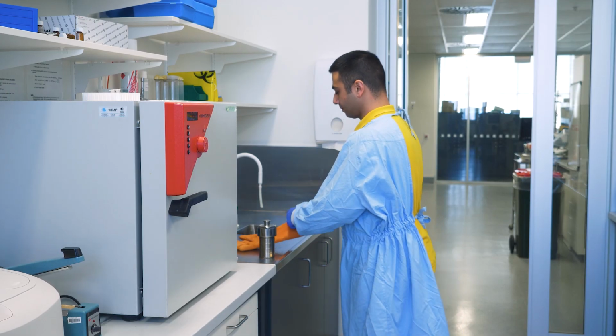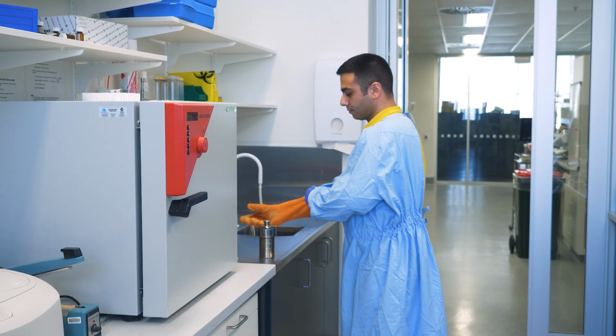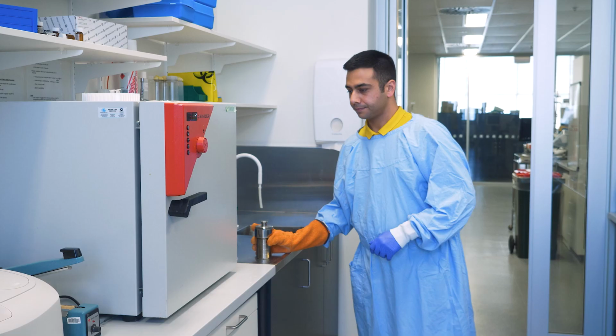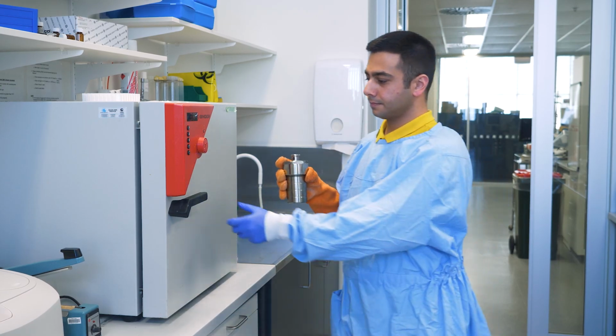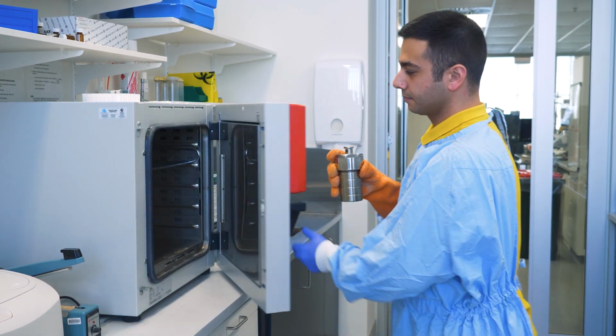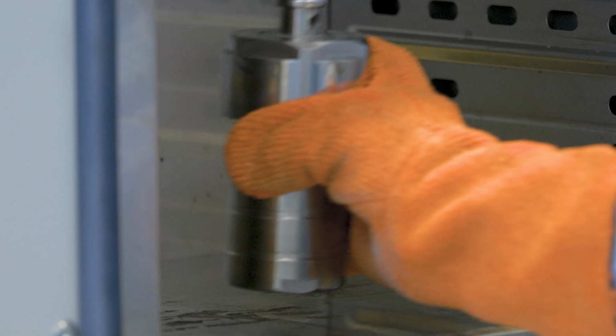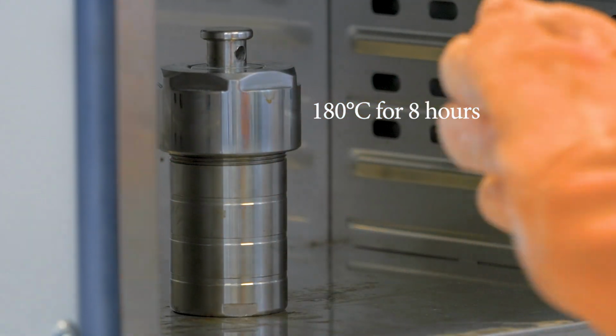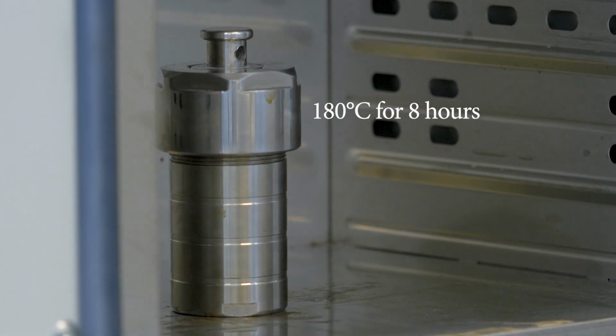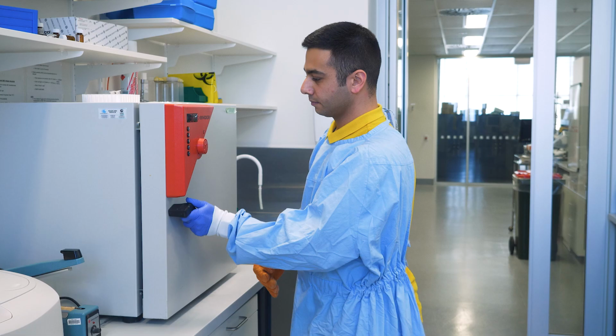Okay, now we are at the furnace. Let's place this in there for 8 hours. I will set the temperature to 180 degrees and set a timer. See you in 8 hours.